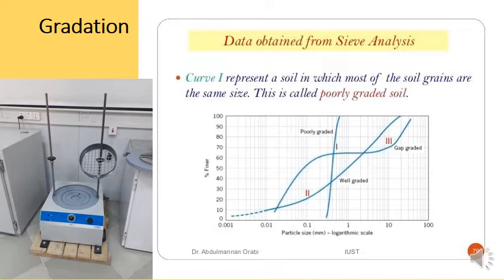And these sieves will have different openings. The ones on top will have the biggest openings, and the ones on bottom will have the smallest openings. And it could be anywhere from about 40 millimeters down to about half a millimeter. And we will place a sample of the aggregate in the top, and then we will shake it. And different portions of the aggregate will get stuck in different sieves.